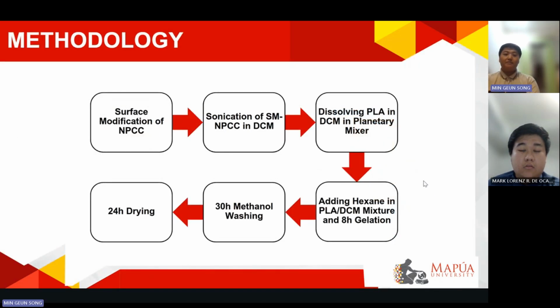For the methodology, we begin with a surface modification of NPCC. In a beaker, 20 grams of NPCC was dispersed in 50 grams of water and kept at 100 degrees Celsius under constant stirring. In a separate beaker, 1 gram of stearic acid was mixed with 20 grams of water and 1 gram of sodium hydroxide.